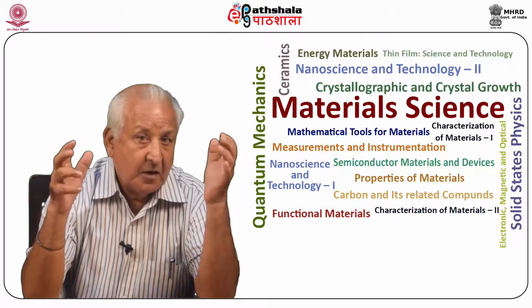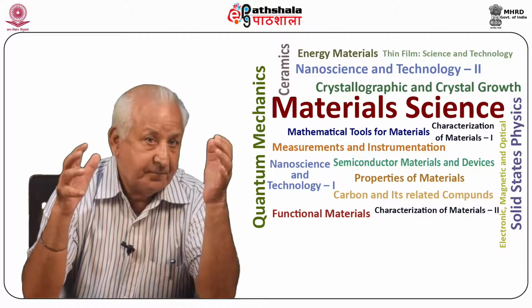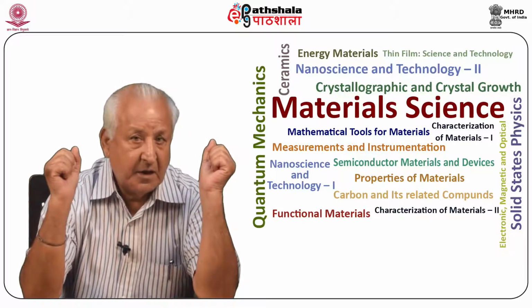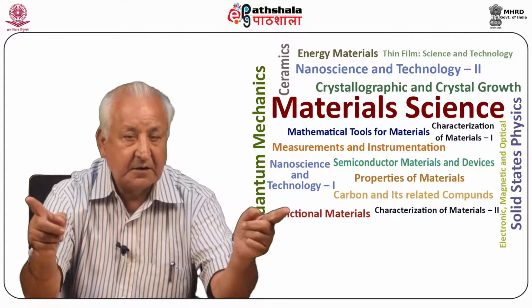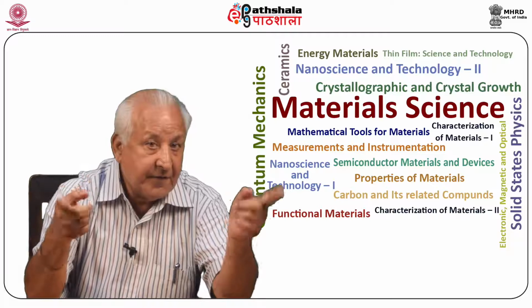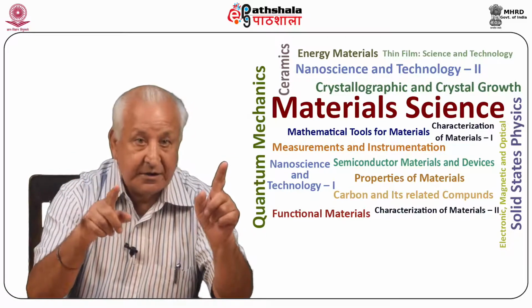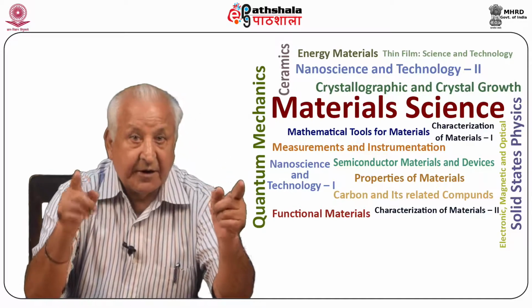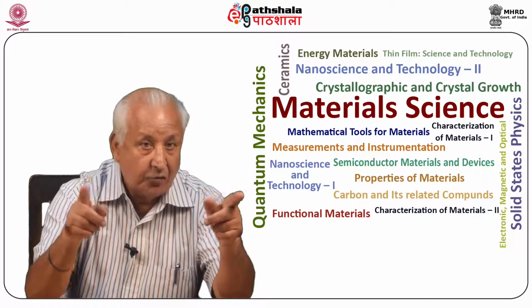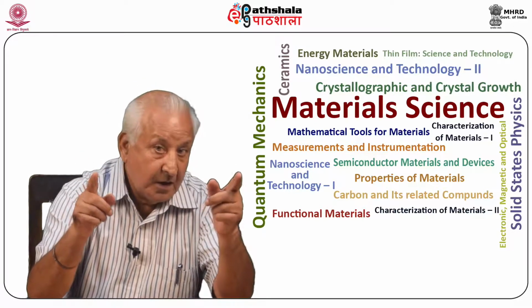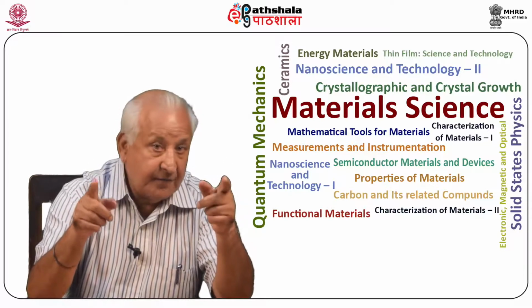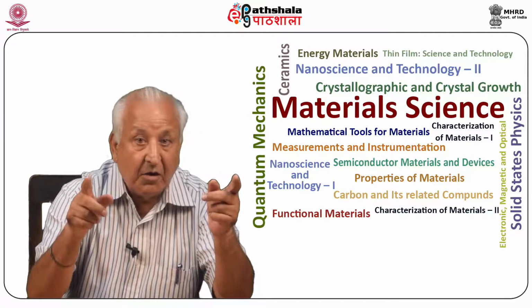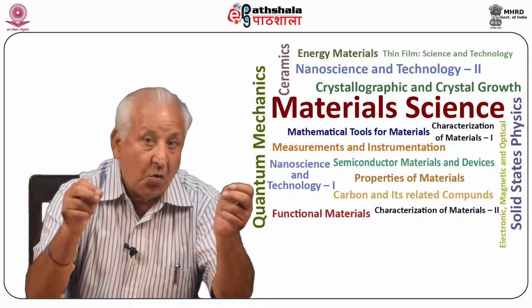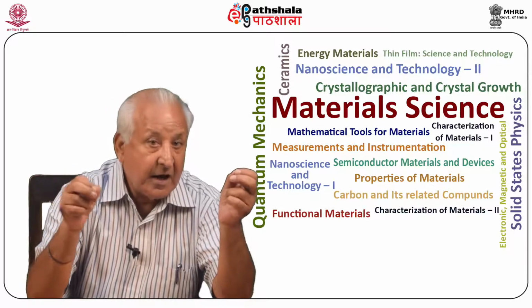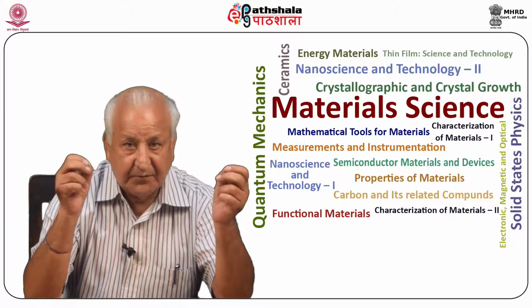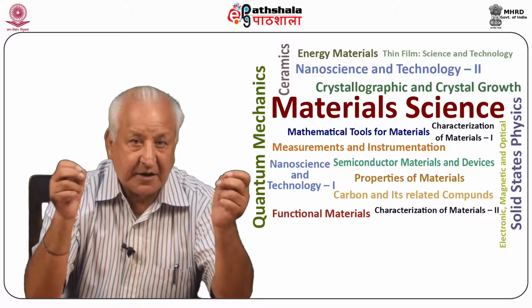If the sphere, known as Ewald sphere, does not pass through any points, it will suggest that the particular wavelength in question will not get diffracted by the crystal in that orientation, and readjustment of orientation will have to be carried out for diffraction to occur. Now, X-ray diffraction can occur only if lambda is less than 2a, because a sphere with radius PO equal to 1 upon lambda greater than 1 upon 2a cannot pass through any point on the lattice, and as such, the above said construction cannot be done.